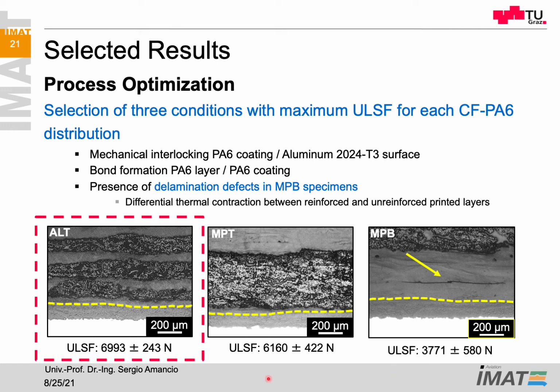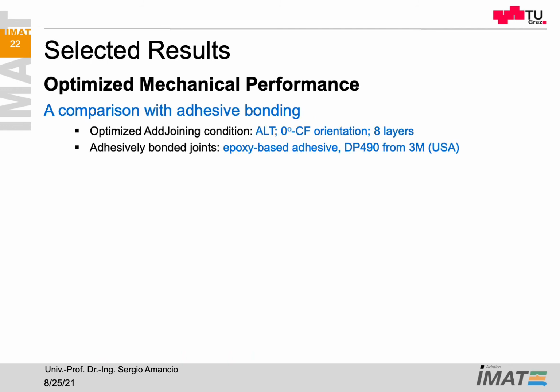Therefore, we went to the alternate condition. The alternate condition has a very low standard deviation compared to the other ones, and this was then used for the comparison that will be shown in the next slide. So here we took the optimized condition and compared that with adhesively bonded joints. The adhesively bonded joints were produced following aeronautic and aerospace procedures in the industry. Also, we used an epoxy-based adhesive, which can be bought commercially, normally used in aircraft applications.